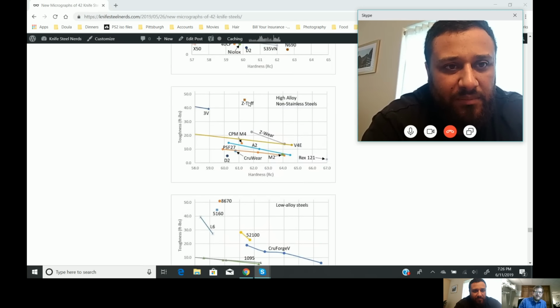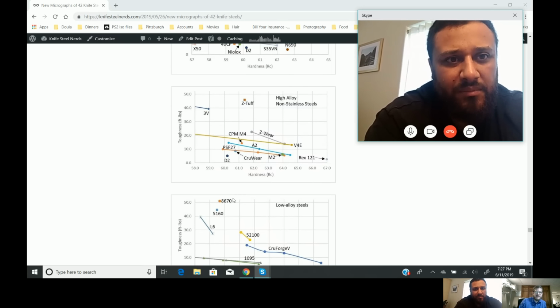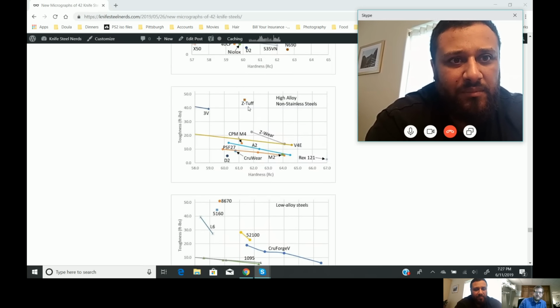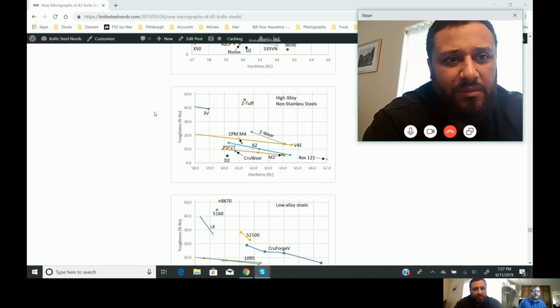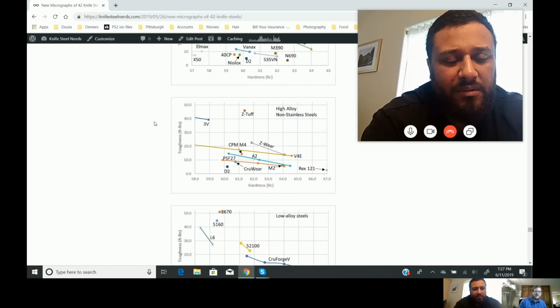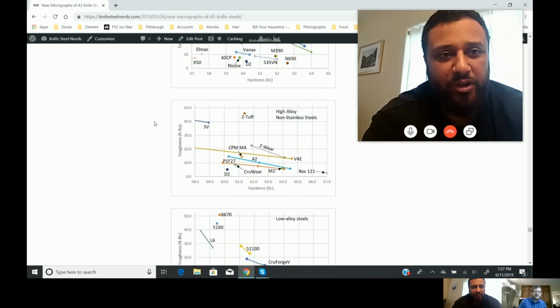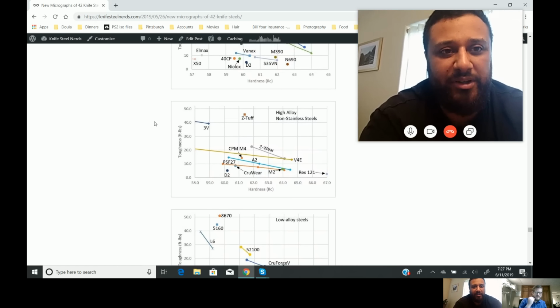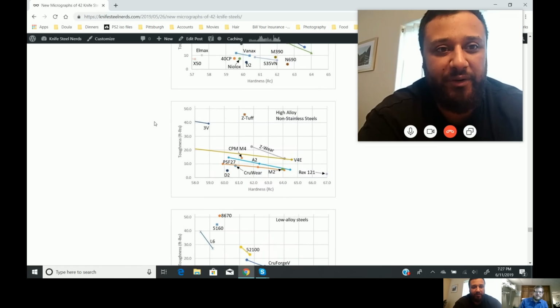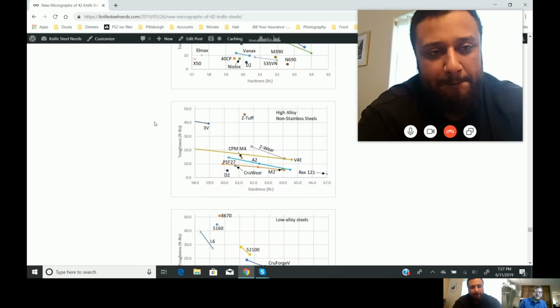Then Z-Tuff has the highest toughness of anything that we've done over 60 Rockwell. So it's nearly as tough as the 8670, but at 61.5 Rockwell. So the Z-Tuff looks really interesting. It's got a little bit of vanadium carbide for a little bit of wear resistance, but just as tough as anything. We saw the pictures; they look the same, but the carbides themselves were harder. So we have that toughness, and then we have much more wear resistance and hardness as well. That's really cool. It's an interesting one.